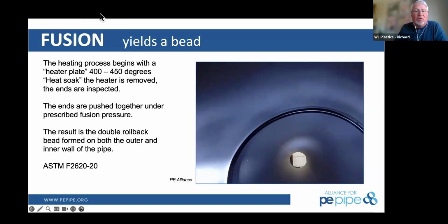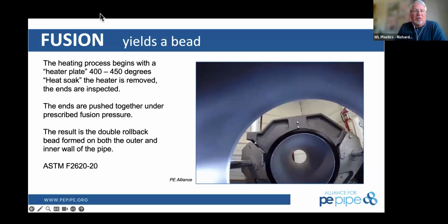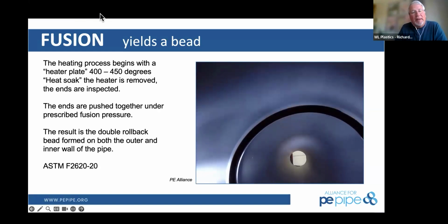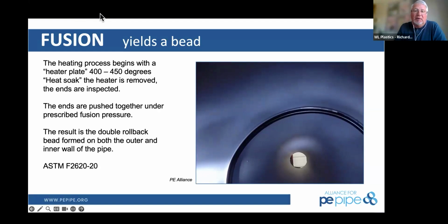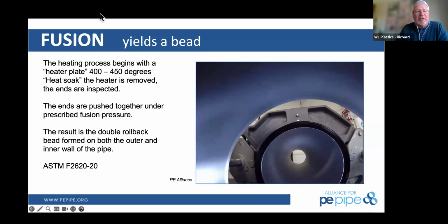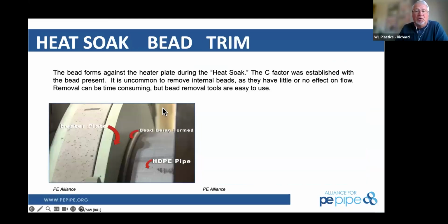In larger diameter gravity flow systems, where sometimes you'll have a big sewer line of 54-inch diameter, those beads can get quite large. So depending on the grades, and anything less than 3% grade, we can remove those beads from the inside. But typically in a high flow situation, nothing will adhere or stick to the polyethylene, and it also doesn't promote any biological growth either. That flow will remain the same over time. So low flows in gravity systems with slow grade or light grades, you'll get some buildup behind those beads, but in reality, in a pressure pipe system, you do not need to remove those beads at all.